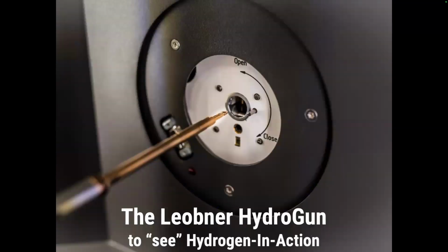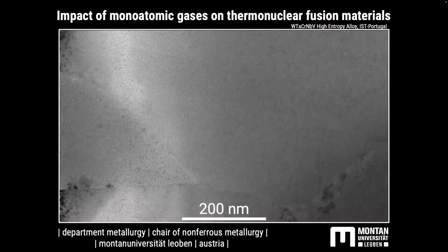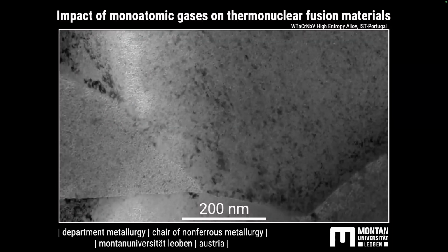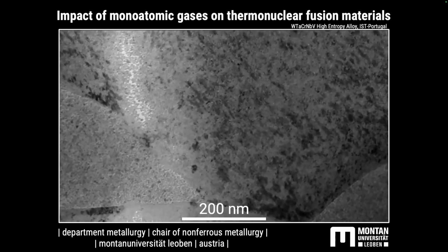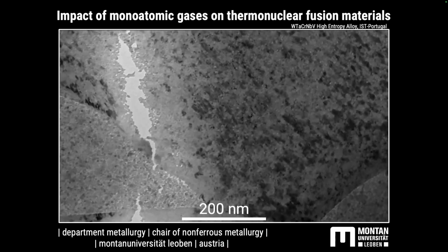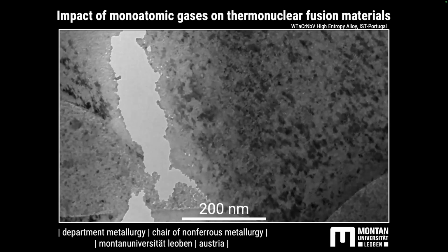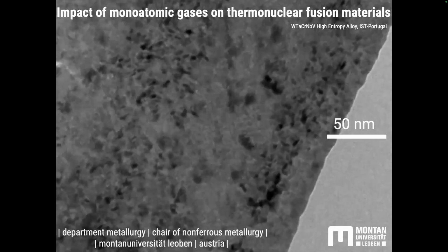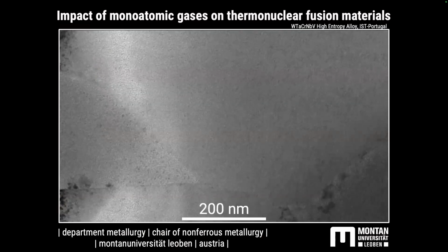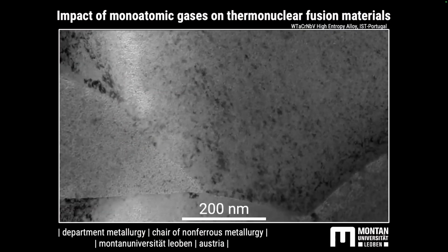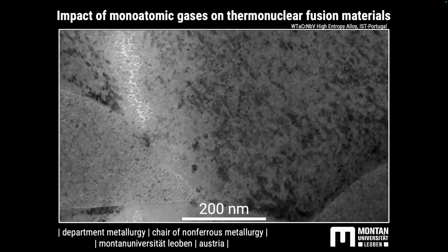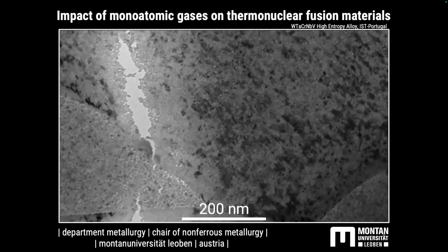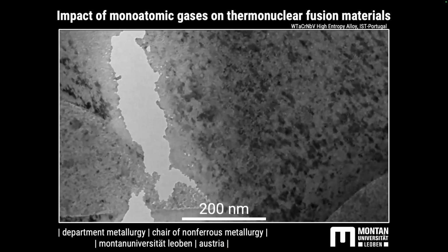So in this project, we are going to develop the Leobner hydro gun. This is going to be a TEM holder with which we will implant hydrogen at very low energies, 0.5 kV. We demonstrated the concept with helium. This is a high entropy alloy. You are seeing directly the helium implantation. I created the indent here with a FIB. When we implant, what you see at the beginning is the formation of dislocations. Then there is a transient where the dislocations accumulate, but this concentrates stress, and we have a crack forming.